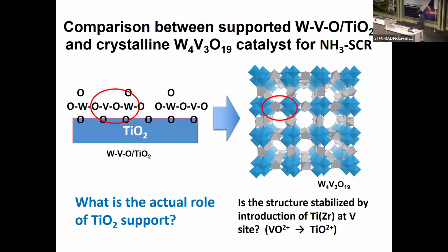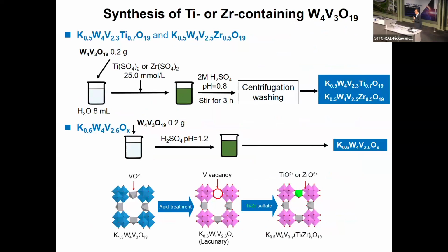That's very simple. Industrial catalysts always use titanium oxide. Why titanium oxide? There's no reason; I don't have any clear answer to this. But titanium might have some stabilization effect on the surface complex. So I tried to introduce titanium into these materials in a way which is very simple, but I don't want to go into the detail. Just after acid treatment, you can remove some of the vanadium from here to form a vanadium vacancy. This vacancy can be supplied with the existing titanium or zirconium cationic species. Then you can get these materials.